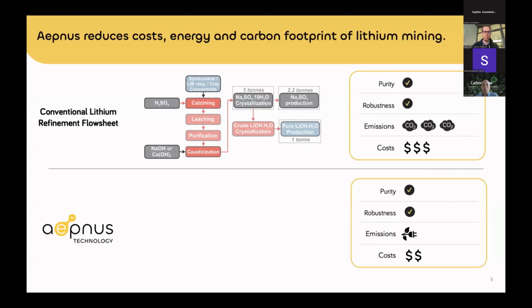For this purpose, usually sodium hydroxide or lime, calcium hydroxide, is added in a big reactor. Lithium is, as a consequence, produced as lithium hydroxide with a significant sodium sulfate waste stream. It's the disposal of this sodium sulfate waste stream, together with these reagent chemical inputs, the sulfuric acid as well as the sodium hydroxide, that make up the majority of costs associated with this process. And it's also these last two steps, especially the addition of the sodium hydroxide to crystallize out the sodium sulfate and the lithium hydroxide, that generate the majority of emissions associated with lithium manufacture, generally speaking.